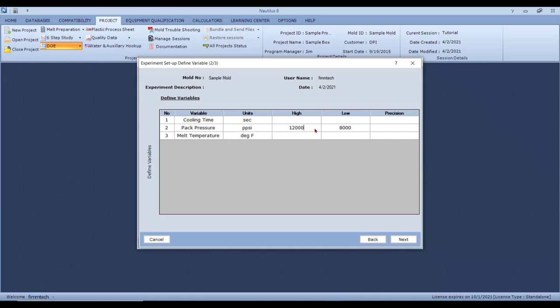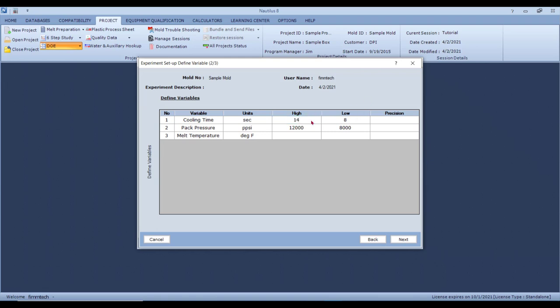Same thing with the cooling time — let's say that below eight seconds you get pin push, and therefore my minimum cooling time would be eight seconds. Depending upon the part thickness, I typically add about six to eight seconds. Let's say it's a part about 80 to 100 thousandths thick, which is about two to two-and-a-half millimeters. In that case, the low is eight and the high is 14.